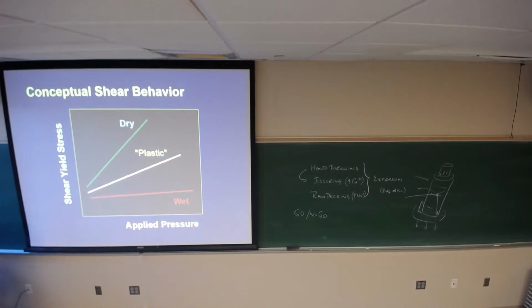This turns out to be wrong. Okay, and we learned some things in the process. Turns out that this is plastic. So what you get is that for plasticity in these systems, the pore space has to be saturated with water. You cannot have an undersaturated system. You fill the pore space with water, and then what we've learned is that you need a little bit of excess water to provide room for particles to rearrange. And what's unique about clays is that they automatically generate that excess water level necessary for flow. And they do it because of the shape of the particles.